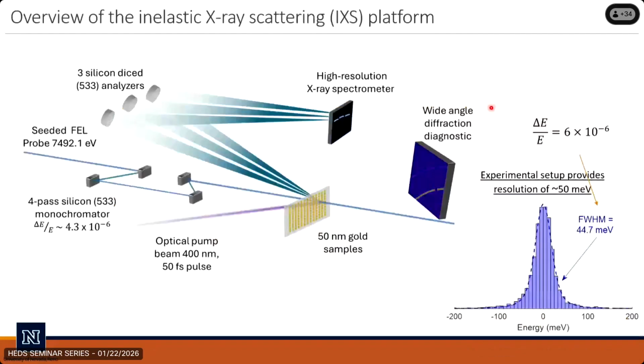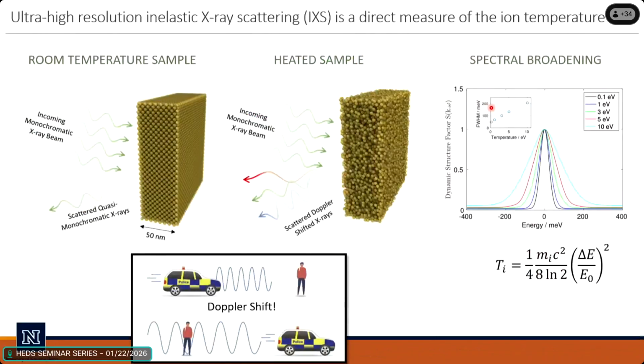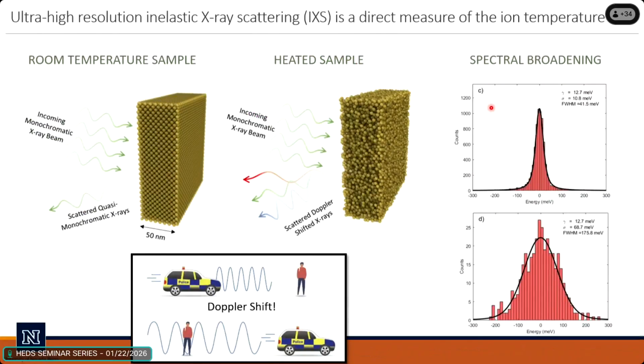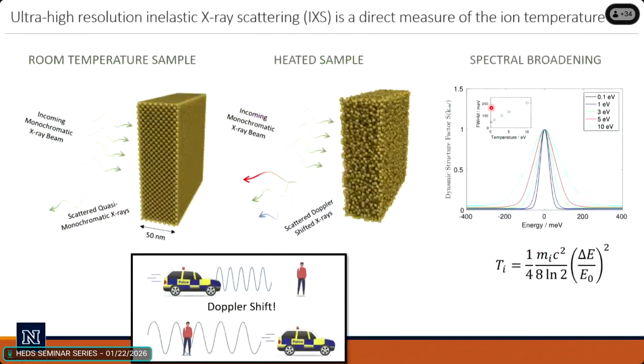I don't know. My guess is that in this broadened spectrum, you'll see from this equation in the bottom right that the broadening is related to the ion temperature, but also the mass of the atom or the ion. And so if you were to have a compound like CH, even something simple like that, then you're going to get two spectra superimposed on each other, and each will scatter proportional to roughly the Z² of the ion.